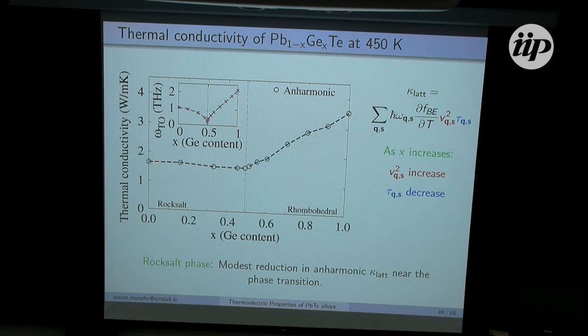But as we get nearer the phase transition, the germanium content is increasing, so our masses are getting lighter, so group velocities are actually increasing. So this results in the group velocities competing with the reduction in the phonon lifetimes, leading to this very modest reduction in the thermoconductivity.